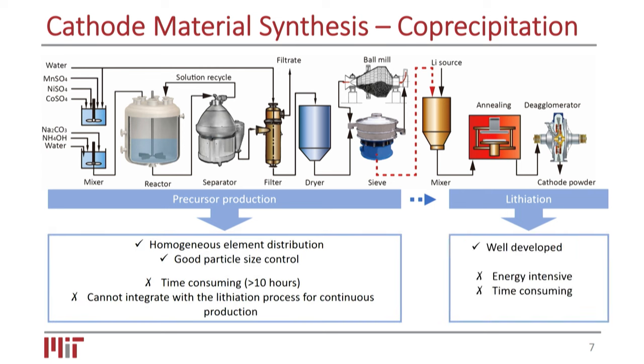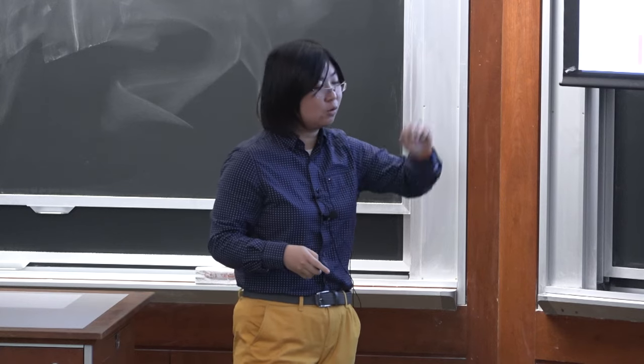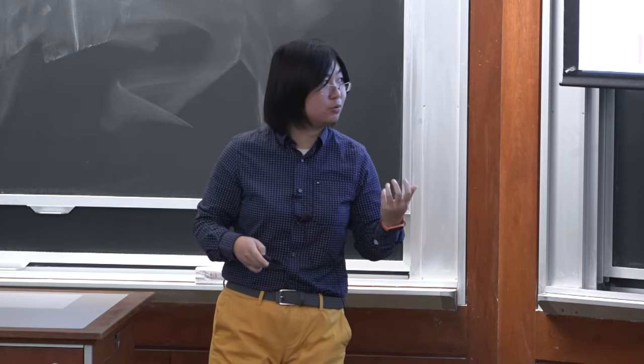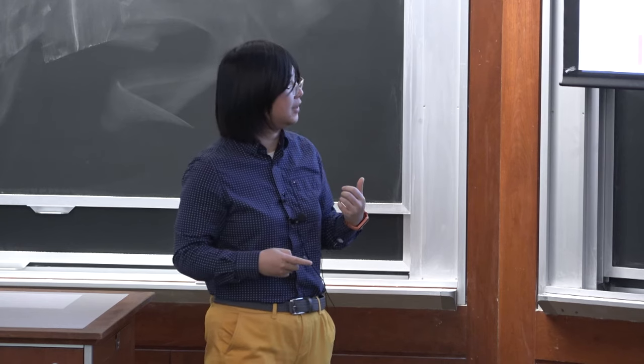So a quick recap of this process: in the first stage of precursor manufacturing, we leverage the good atomic level mixing in the liquid phase. And we can control the size relatively well, but the whole process is normally batch-based. It takes time to react, and the reaction rate in the solutions isn't great. So it takes about 10 hours for this process to happen. And in the second step, because of the solid state mixing, we experience a high energy demand and consumption in this process, and it is also very time consuming. So both stages have room for improvement to help us scale up the production significantly.